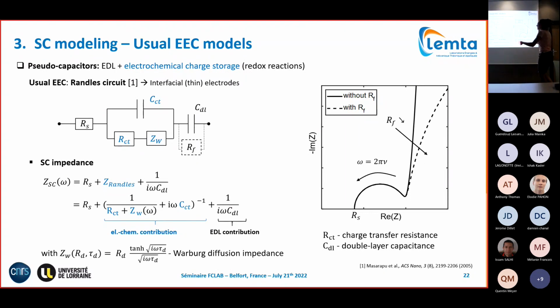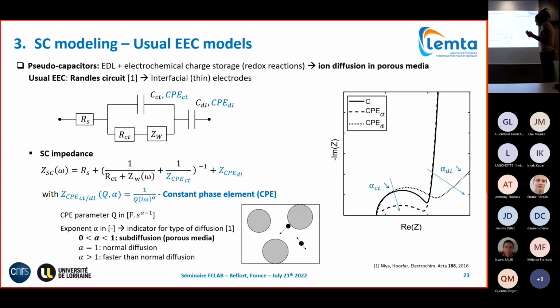Just note the Randles circuit has a crucial hypothesis. It supposes that your charge storage is done at an interface between the electrolyte and the electrode. It is typically associated with interfacial, thin electrodes. So usually it's a contradiction for supercapacitors, which have porous spaces, so you have thick electrodes. So this was the major point, we will come to this later.